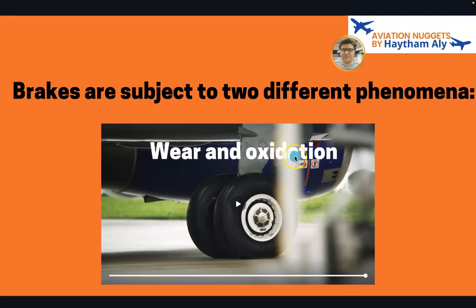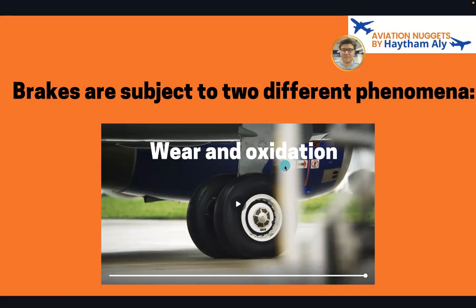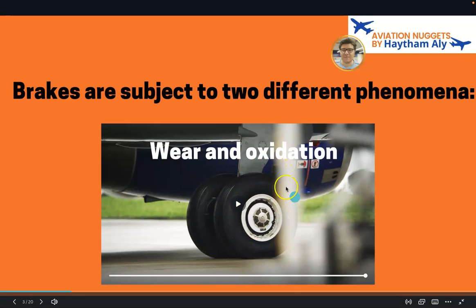Oxidation is a phenomenon where the carbon reacts with oxygen in the air. Carbon in the carbon multi-disc brake reacts with the oxygen in the air, so the carbon becomes like powder, like ashes, and the brake heavily loses its strength and mass, and cannot absorb the required heat. You know that the brake unit is called a heat sink because it absorbs the heat converted from the kinetic energy by the carbon multi-disc brake.